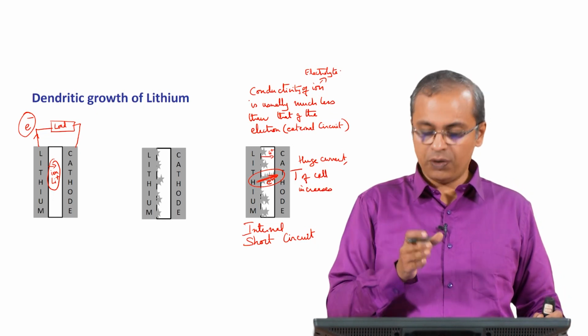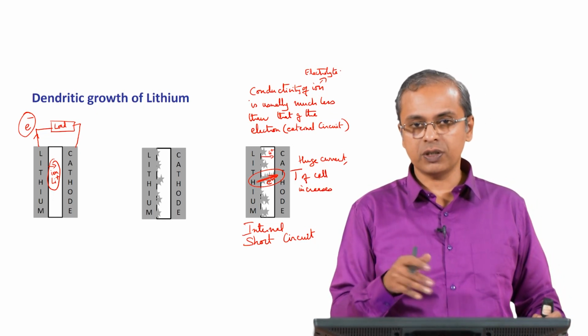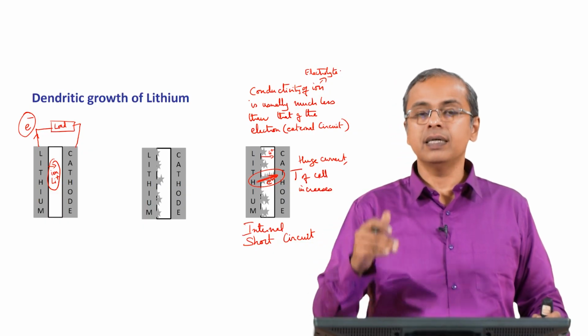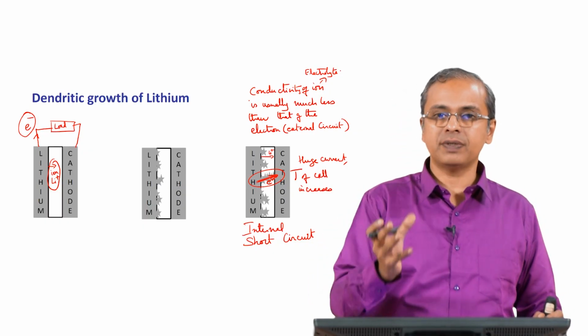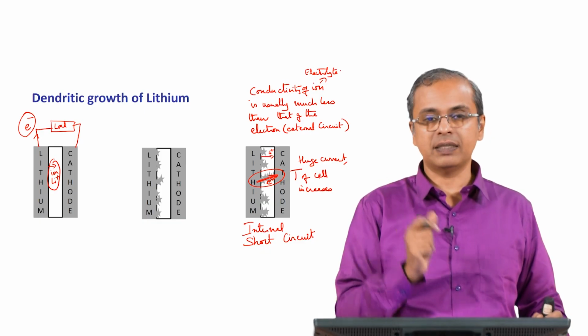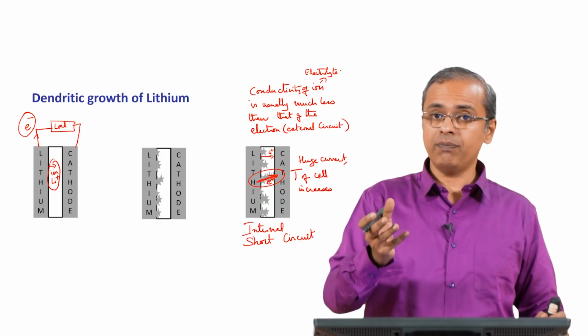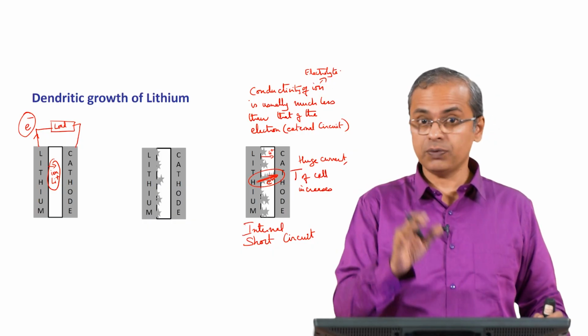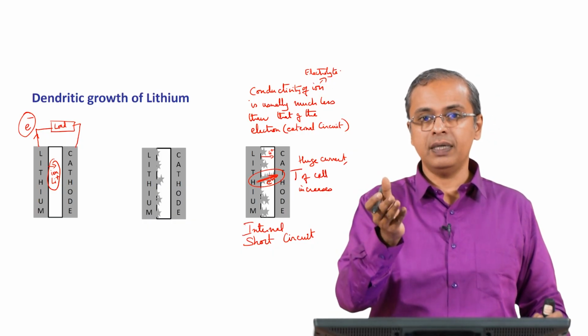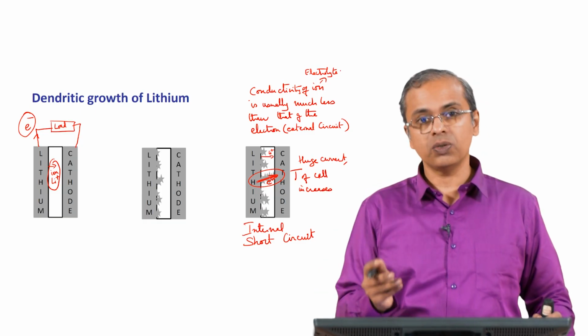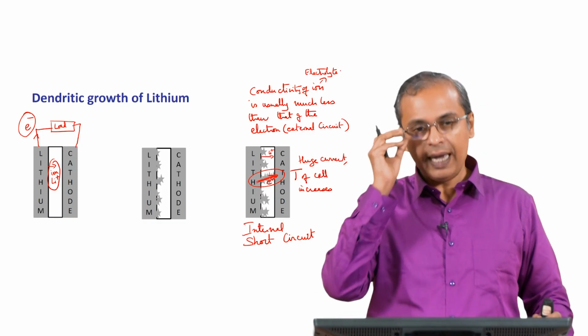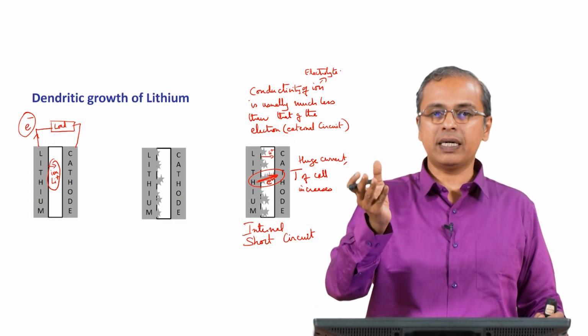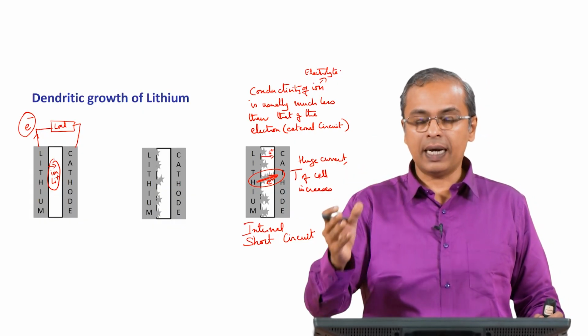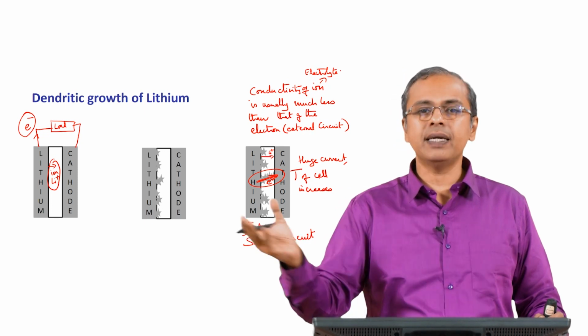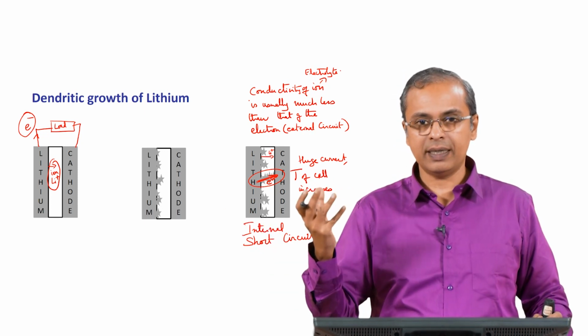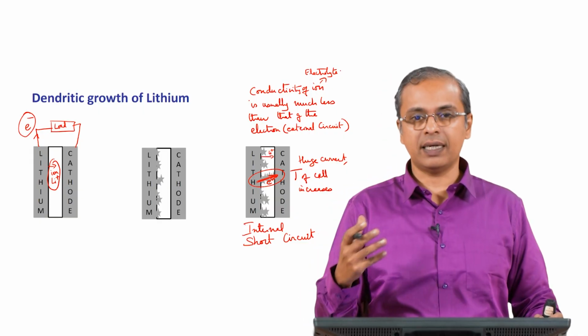So, that is because you are having internal short circuit, because of the internal short circuit lot of current is flowing in that path. Because lot of current is flowing in the path, temperature of the cell is going up, you can physically feel the cell has started becoming warm. Because it has become warm, the ionic conductivity has gone up, which was the slowest step previously, now that has gone up. If that has gone up, the current in the original short circuit goes up even further. Okay. So, again it heats up even further, ionic conductivity goes up. So, this is an unending cycle, it just increases rapidly and it can explode. So, the lithium battery can explode, basically it has an uncontrolled reaction, it can explode.